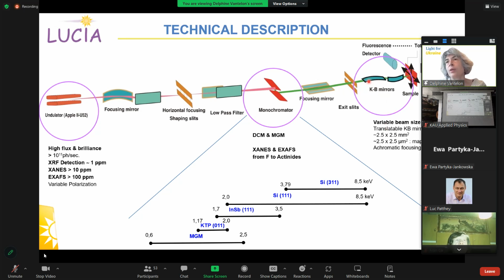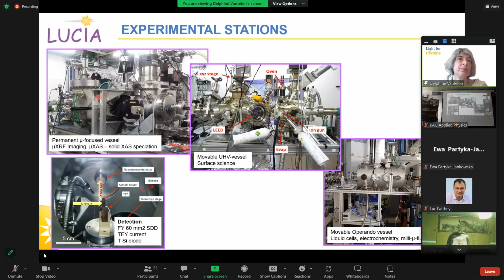To have the focus or the macro beam size, and then the beam enters into the experimental chamber. You have a picture here of the permanent experimental chamber and an image of the inside of the chamber here. We have 3 methods of detection that can be used together. A fluorescence detection with a 60 square millimeter SDD currently. We can also measure the current of the sample, and then we get the total electron yield. And we can also measure transmission, if possible, using a silicon diode installed after the sample.